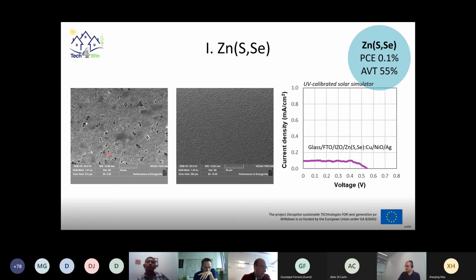We have been able to avoid it in the meanwhile for the thick layers, as you can see on the right, the middle SEM top view picture, where we have been playing with some pre-annealing in nitrogen, and the ramp up for the selenization/sulfurization was also very fast in that case. However, I also have to be honest, for the thinner layers, it seems to be even more difficult. We did already do some process optimization, but we still have to do more.